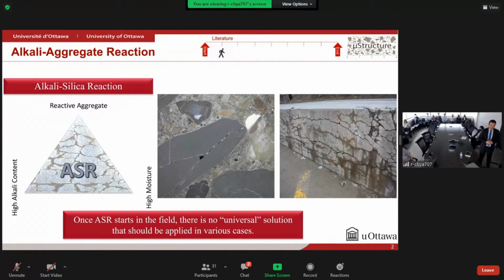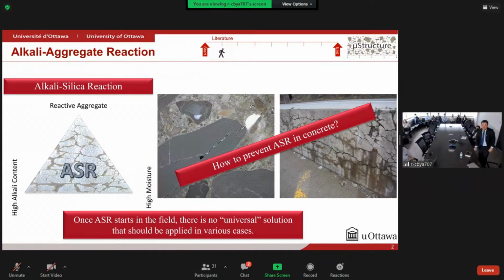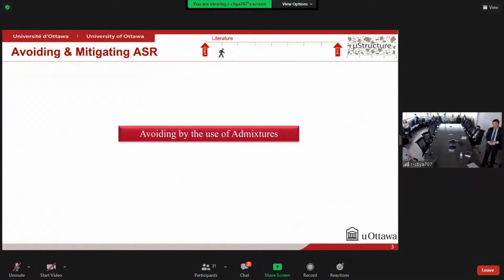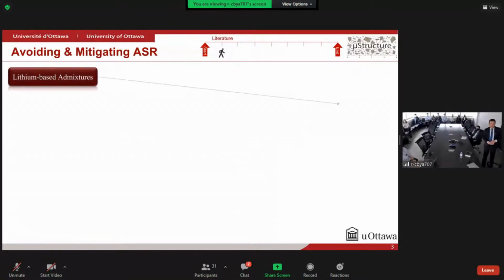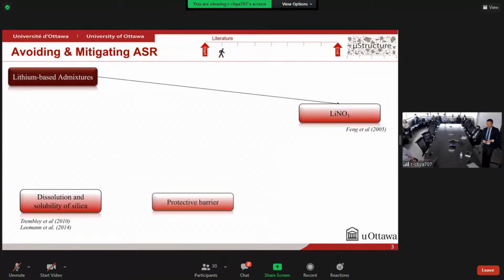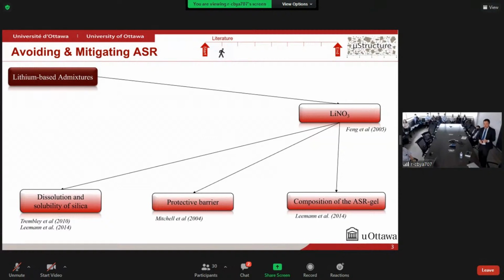And once it starts in the field, there's no universal solution that could be applied in different scenarios to mitigate the reaction. So the thing here is that we should act to prevent the reaction from happening. So what can we do to prevent the development of ASR in the field? One of the ways is through the use of chemical admixtures. For example, lithium nitrate, which can change the dissolution and solubility of reactive silica, forming a protective barrier surrounding the aggregates and changing the chemical composition of the ASR gel. The problem is that these products are too expensive and their effectiveness is constantly questioned in the literature.